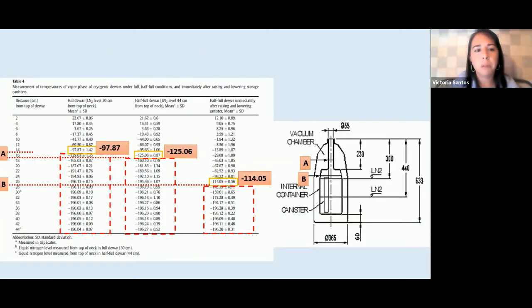Here you can see the temperature at different heights measured from the top of the Dewar. For a full Dewar, you can see that at 14 centimeters, you have reached temperatures above TG. And for a half full Dewar, there is also almost 2 centimeters away that reach -125. That would be around the TG of our vitrification solution. So above, we have risky zones where the sample can enter a rubbery state. What happens if we disturb all this nitrogen vapor in a half full Dewar? Well, we reach the TG at about 26 centimeters. That would be point B in the Dewar, below the neck.